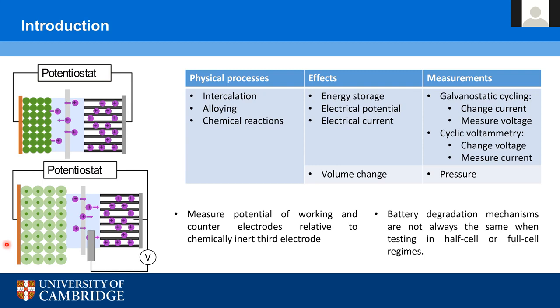This is important because it's important to test full cells. Typically we test a lot of materials just in half cells, so we measure one electrode versus a lithium metal electrode, but it's important to test full cells as well, because the degradation mechanisms in full cells can be quite different to half cells.